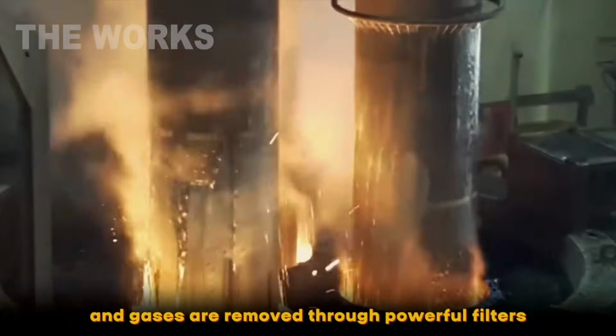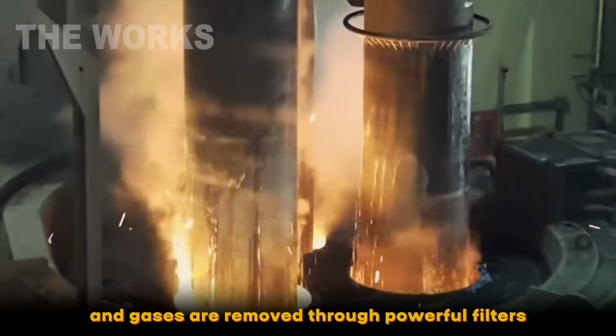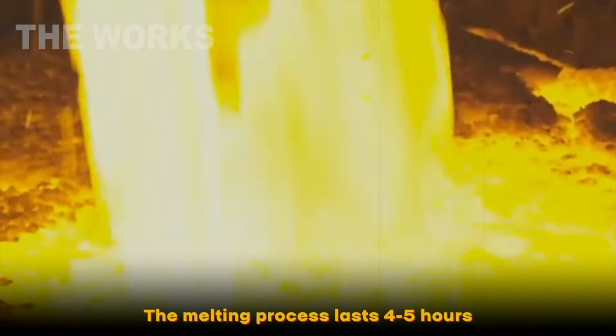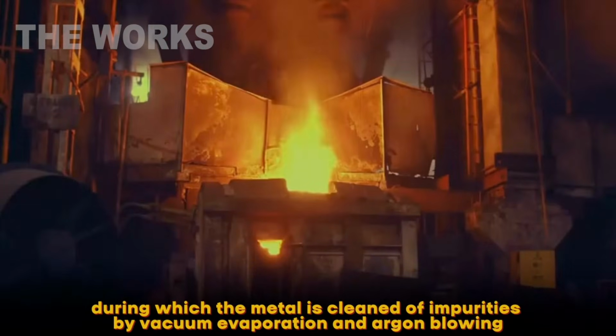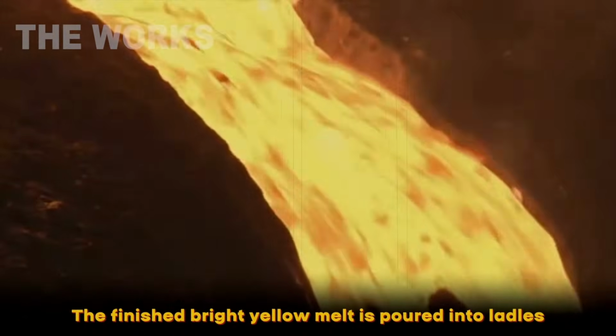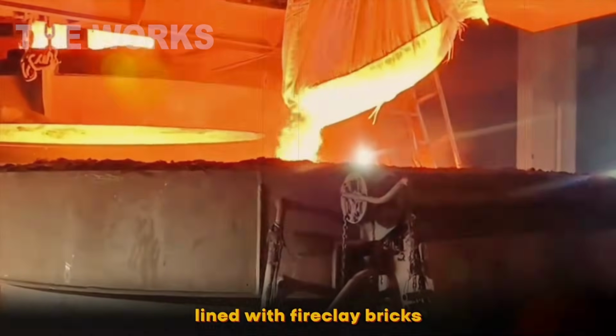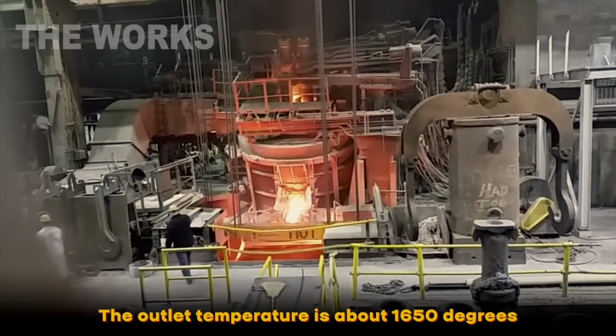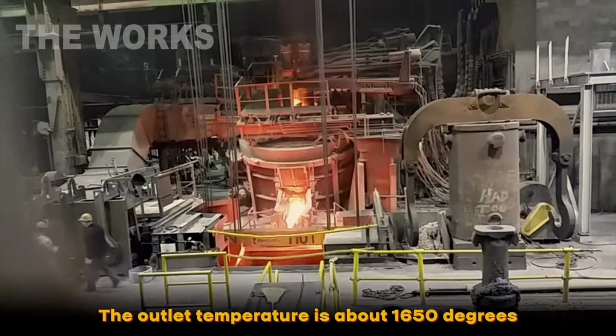The melting process takes 4 to 5 hours, during which the metal is purified through vacuum evaporation and argon purging. The finished melt, a bright yellow color, is poured into ladles lined with fire brick. The temperature at discharge, around 3,000 degrees Fahrenheit. Cranes lift the ladle and transport it to the casting line, where prepared molds are already standing.